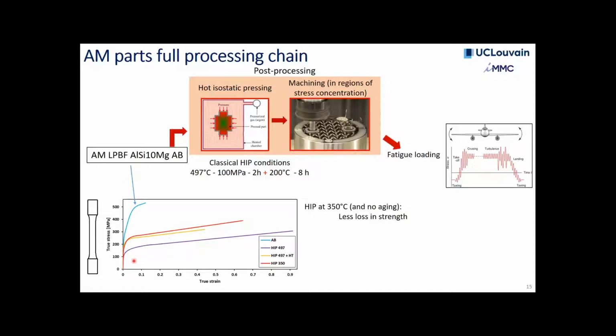So when we saw that, we were very excited about the results. As you can see here, after 497 degrees hot isostatic pressing, we have this large ductility with this huge loss in strength that I was mentioning just previously. Now, after this 200 degrees, 8-hour heat treatment, you can improve the strength a bit, and the ductility is not too bad. So this is reasonably accepted in the aerospace industry and is applied quite commonly on these alloys before